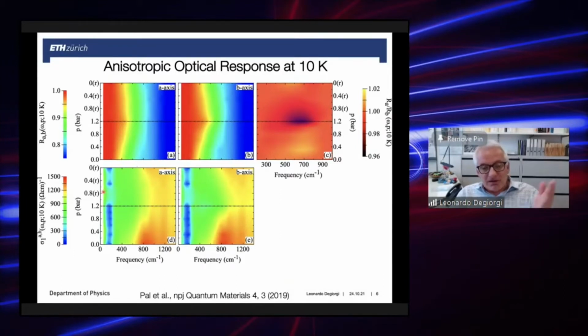These indicate some residual, or basically correspond to the high frequency tail of some residual Drude-like resonance, which is due to the itinerant charge carriers activated across the superconducting gap because of the thermal pair breaking. But again, you see here that upon applying stress, there's an obvious anisotropy. This can be observed if you consider the difference of this quantity between the two axes, which is a measurement of the so-called dichroism.